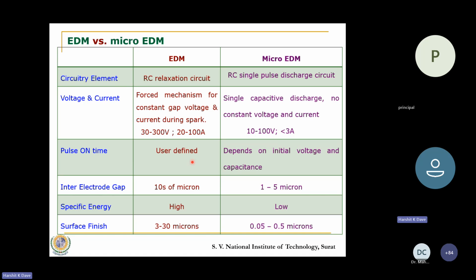The inter-electrode gap between tool and workpiece in EDM is in the range of some tens of microns: 10 micron, 20 micron, 30 micron or so. Whereas in micro EDM, this inter-electrode gap is less than 5 microns, as small as 1 micron. The specific energy available in a single pulse is very high in EDM, whereas you reduce it in micro EDM. The surface finish ranges from 3 to 30 microns, usually more than 10 microns. In micro EDM, it is from 0.5 microns, that is 500 nanometers, to 0.05, that is 50 nanometers. So the capability of micro EDM in generating good surface finish is enormous. So this is the brief comparison.